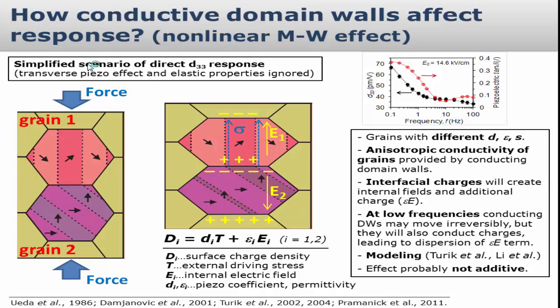In general, how it works is that you have different grains in your ceramics that are differently oriented. They have different piezoelectric coefficients in this direction, that's obvious, because D33 is a function of orientation, and there are other reasons for that. When you press such a material, you will have some piezoelectric charges which will not be totally compensated, because you have different piezoelectric coefficients. From this you will create internal fields, and those internal fields will in turn give you some additional dielectric charge, which adds up to your piezoelectric one. The problem comes with this term: these charges start to change with time, start to drift.